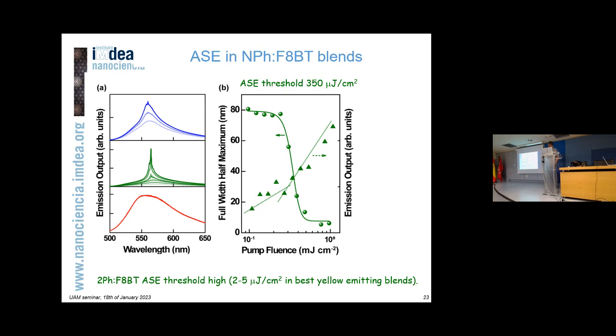If the wave-guided mode is amplified, what you should see is a narrowing of the line shape, because you are only amplifying that mode with respect to the complete photoluminescence. As you see, it didn't quite work for the first blend, 1Ph:F8BT. It worked with 2Ph:F8BT. It didn't work at all with 3Ph:F8BT. This is a spectrum taken at the maximum fluence we have available with excitation.